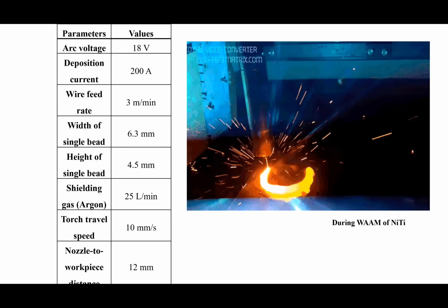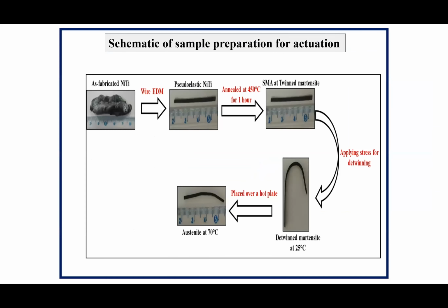Okay. Now, as far as the sample preparation, or the methodology we followed, we built NiTi structures. Using wire EDM, we make small pseudo-elastic NiTi structures, and then we anneal them to activate the SMA-based behavior. By applying a stress, we can have detwinned martensite as well as the austenite phase. By comparing these two, we can achieve an actuation. That is the idea we had in mind. In fact, it was a bit flexible for us, because whichever sample we fabricated, we could evidently see the actuation coming out of it.